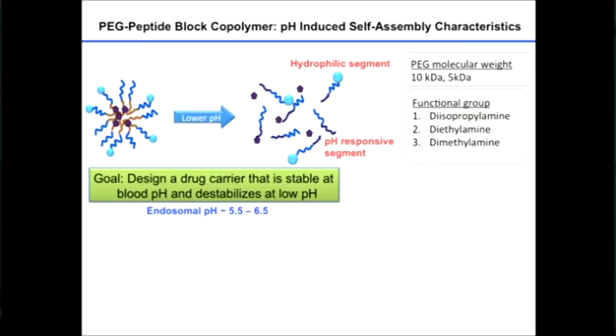So we looked at trying to design the interior of these systems by taking the same kind of polypeptide that we were using before that sequesters the hydrophobic drug, but designing it so that it's hydrophobic at pH 7.4, which is our bloodstream pH, but at lower pH values, it begins to become unstable, becomes more hydrophilic, and therefore becomes water-soluble and releases the drug.